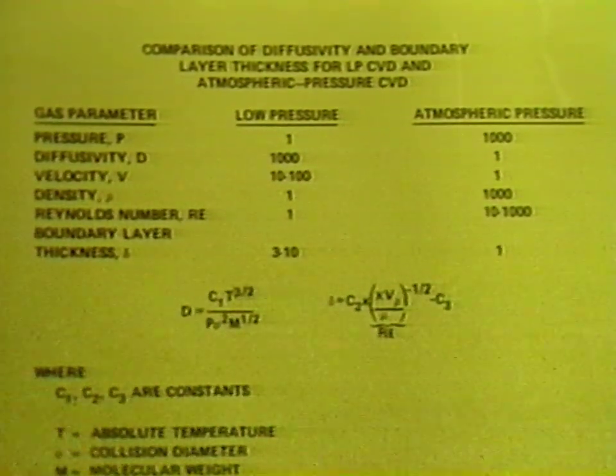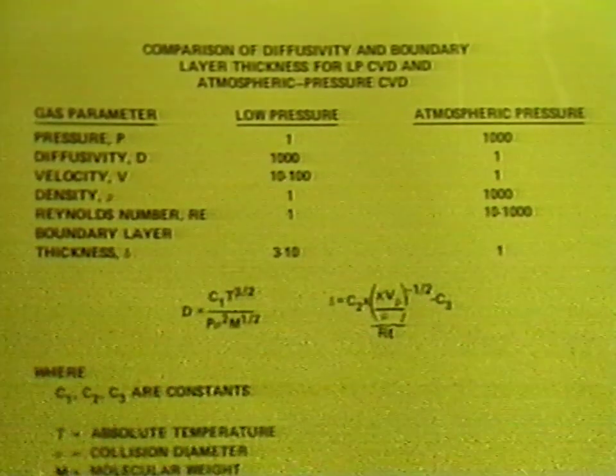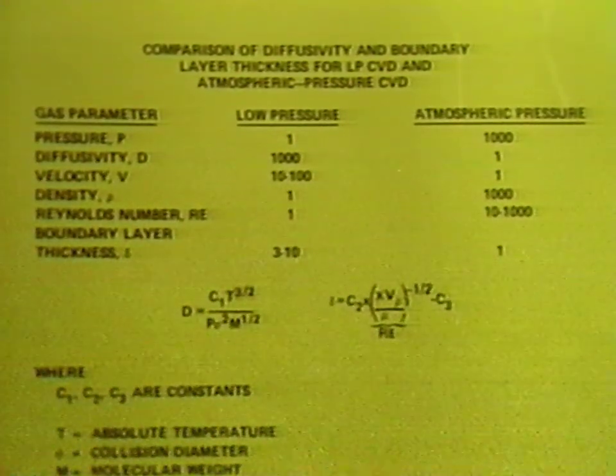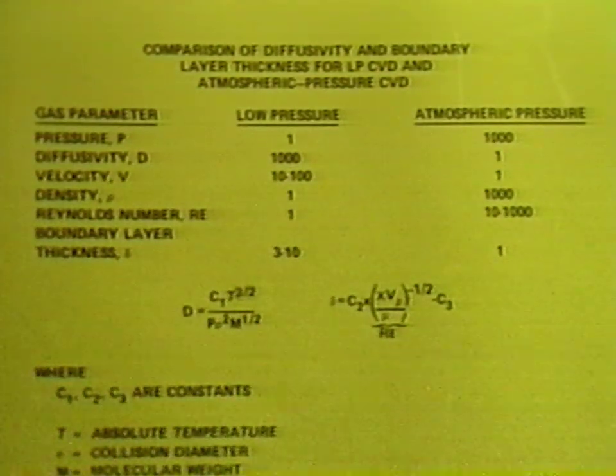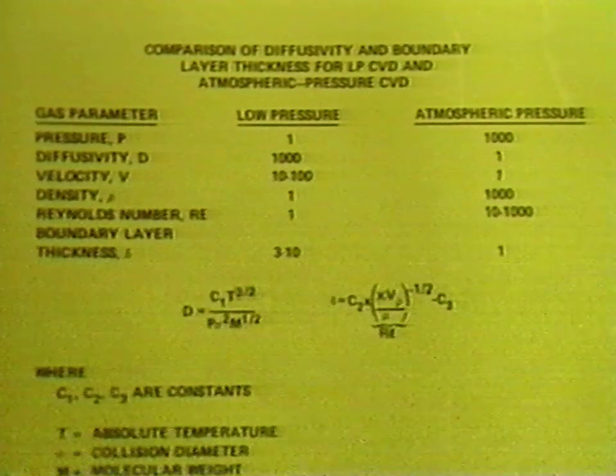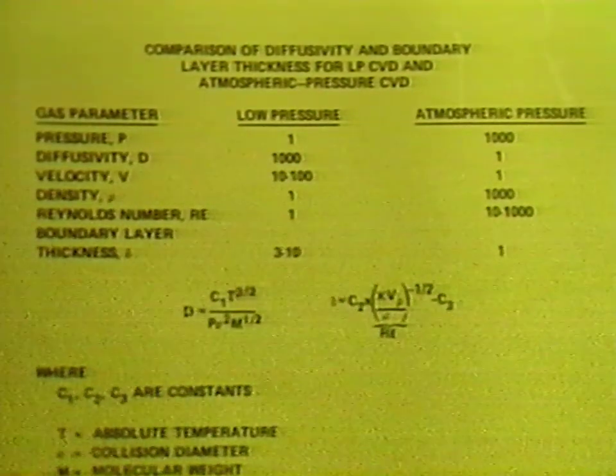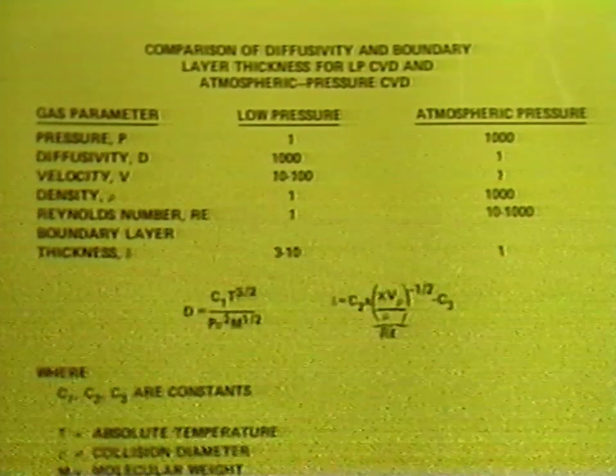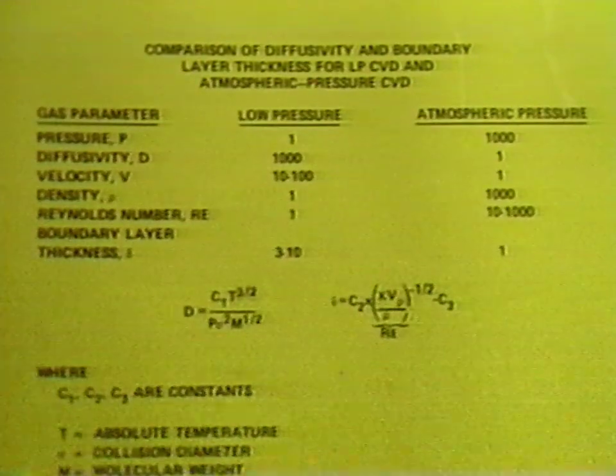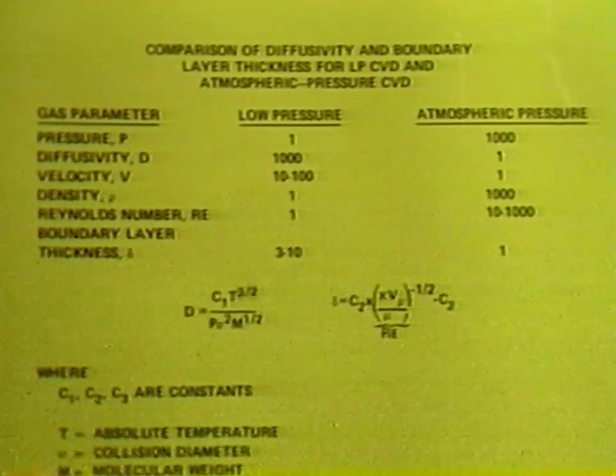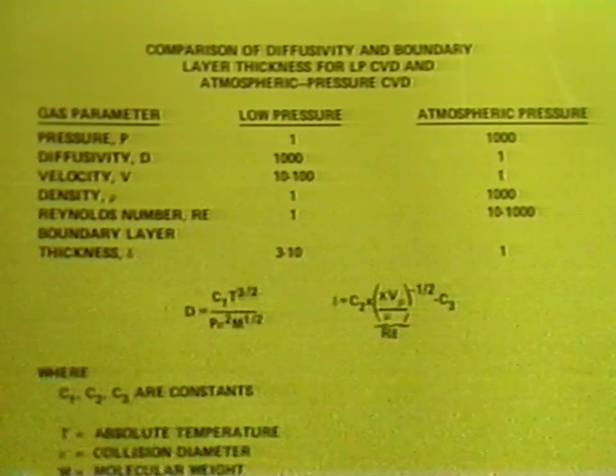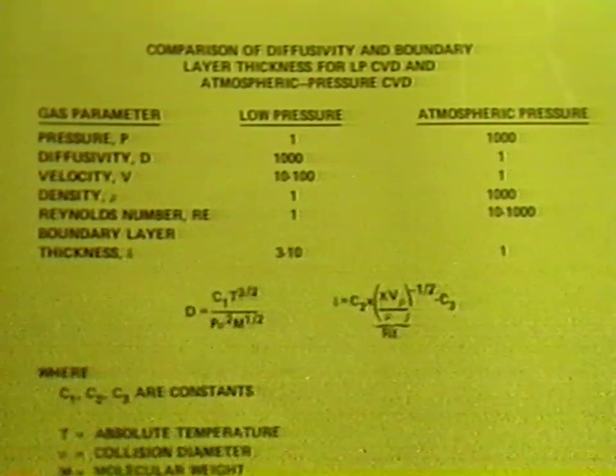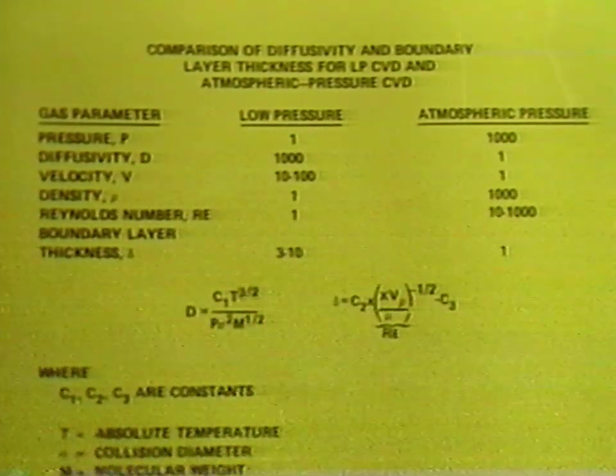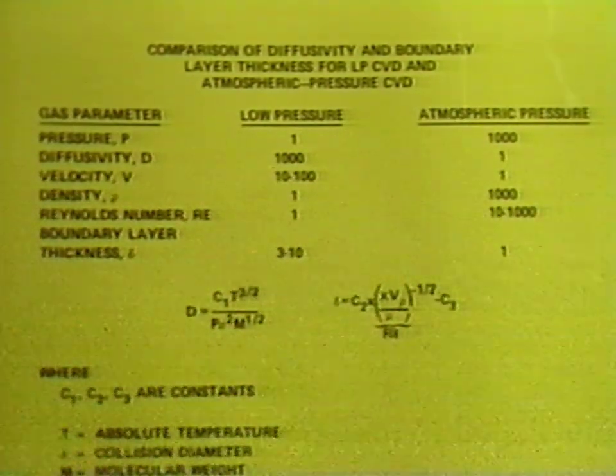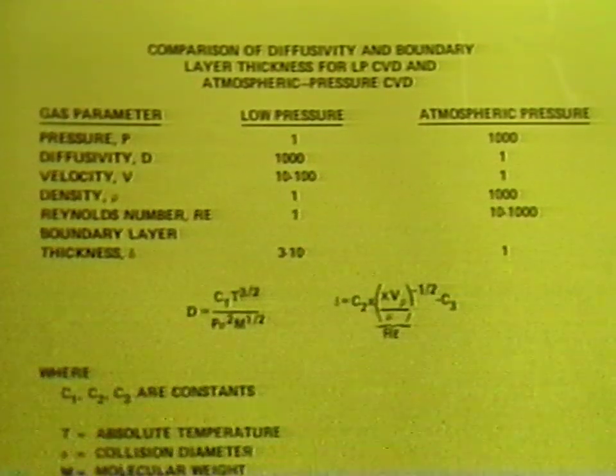Now, if we look very briefly at low pressure CVD compared with atmospheric pressure CVD, essentially what I just went through, but putting it into more concise terms perhaps, in this case looking at the numerical values, we start off with atmospheric pressure CVD at let's say 1,000 torr pressure, and see what happens as we decrease the pressure to 1 torr. We can see what happens to the various factors here: the change of diffusivity from 1 to 1,000, and the velocity change, density change, and also the change of the Reynolds number, being defined down here in this equation.